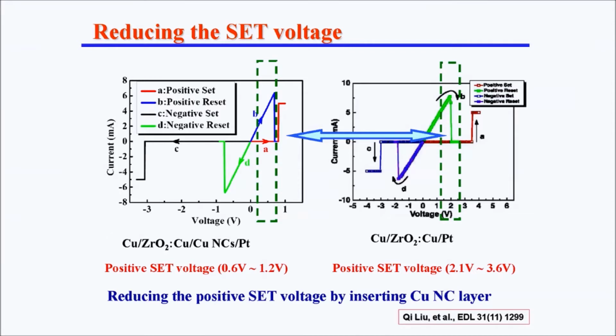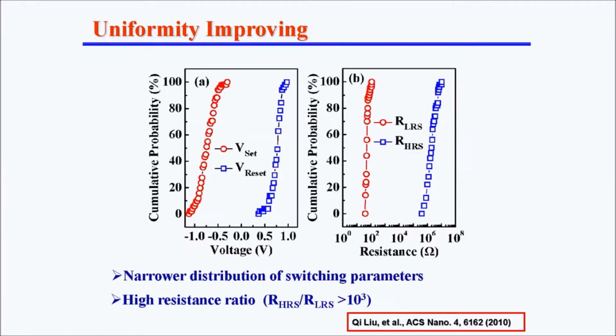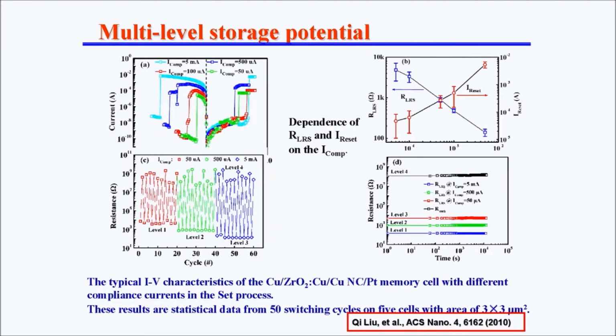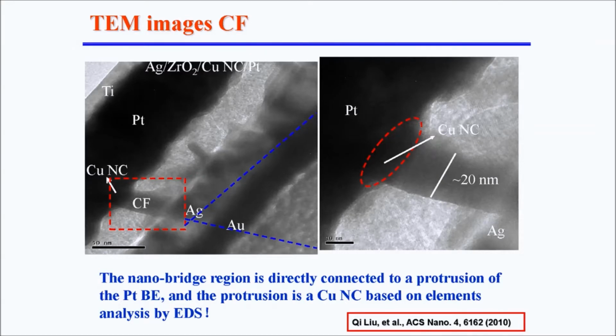So then the fabricated device. We measure this device, and we can see the performance improved dramatically compared to the device without the nanocrystal layer. Also, we can see the uniformity is very good, both the high and low resistance states, set and reset. They also demonstrate very good multiple level storage performance. That's good for high density applications. So let's give the direct evidence that the filament was controlled by the nanocrystal. With the TEM, we can clearly see this filament growing along this nanocrystal. This is hard evidence that we can control the filament growing around the nanocrystals.